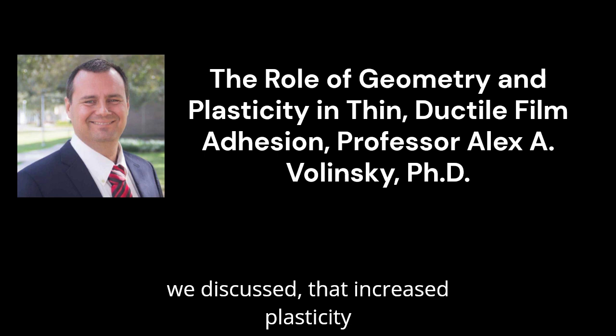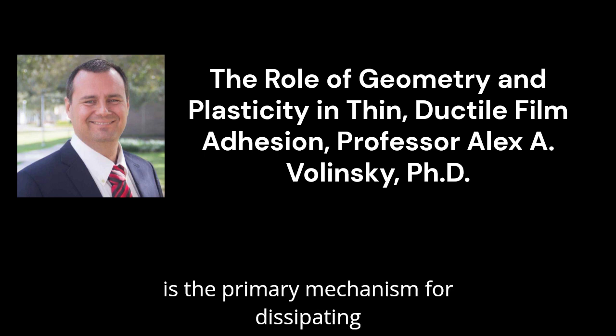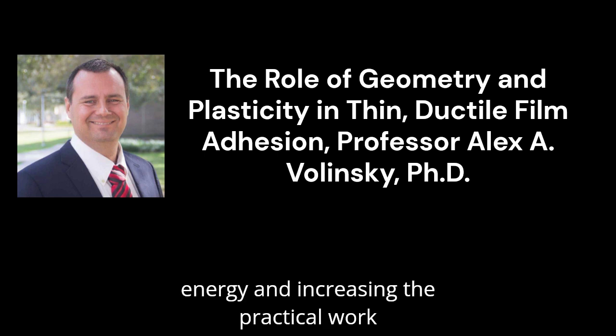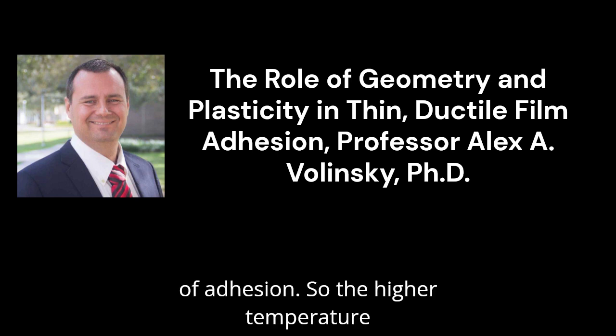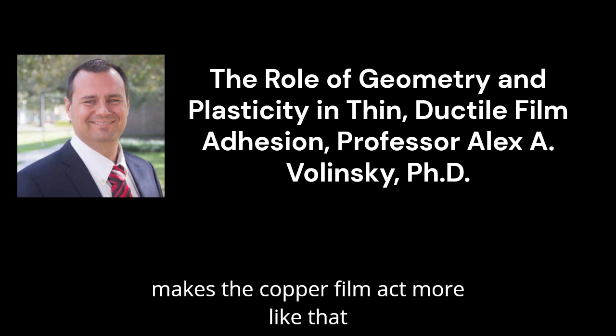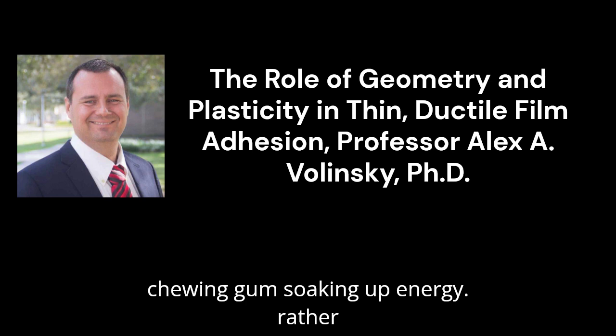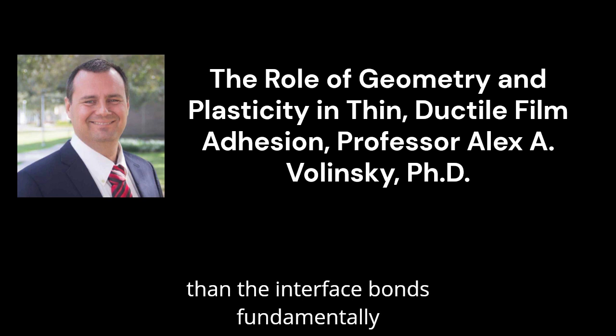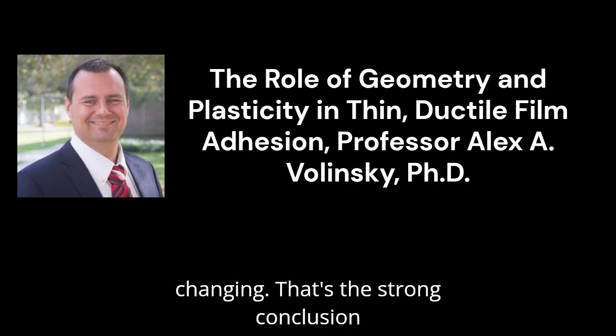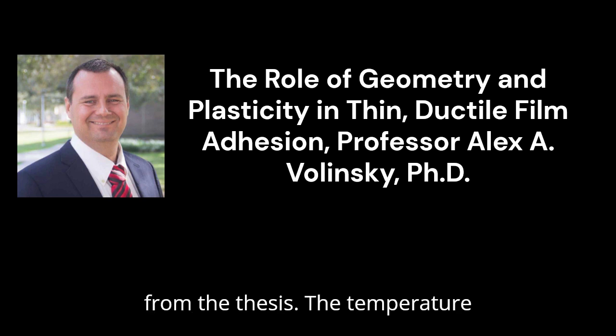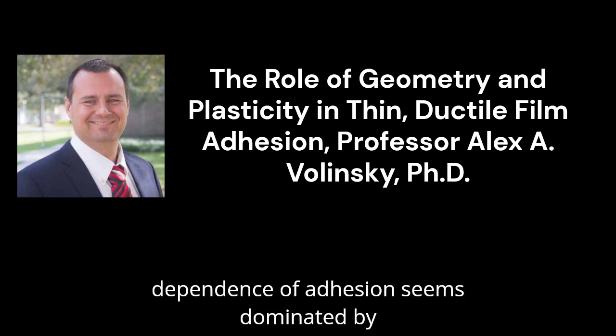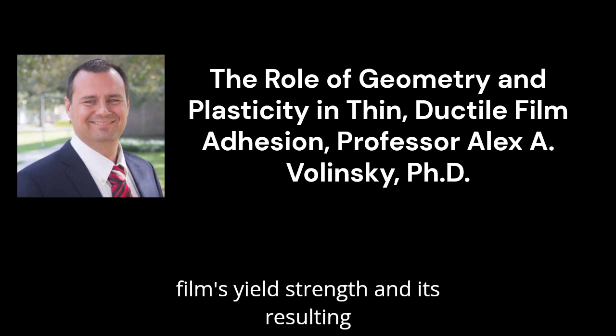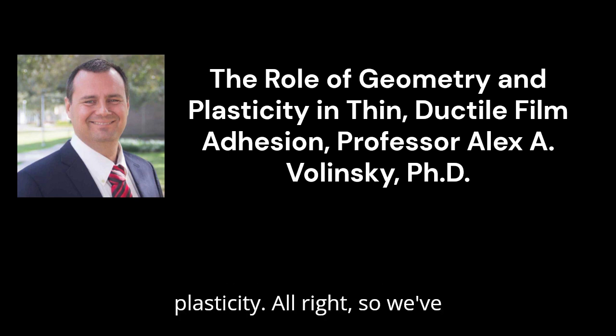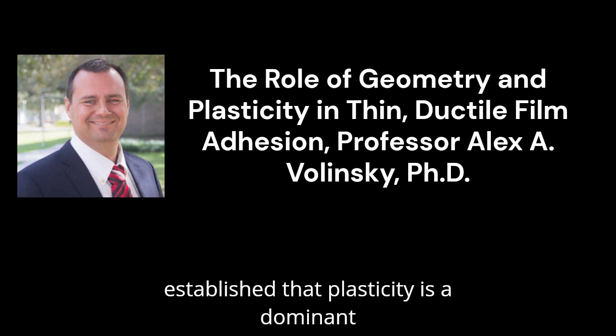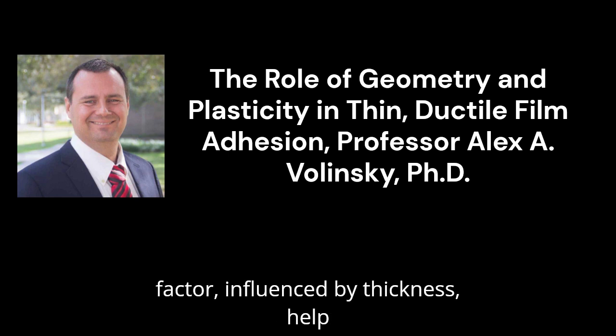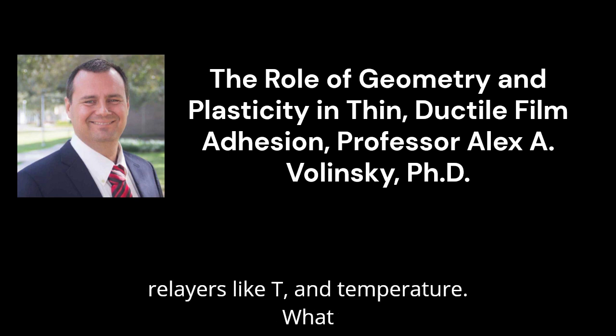And as we discussed, that increased plasticity is the primary mechanism for dissipating energy and increasing the practical work of adhesion. So the higher temperature makes the copper film act more like that chewing gum soaking up energy, rather than the interface bonds fundamentally changing. That's the strong conclusion from the thesis. The temperature dependence of adhesion seems dominated by the temperature dependence of the copper film's yield strength and its resulting plasticity.